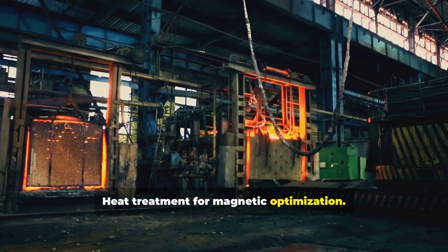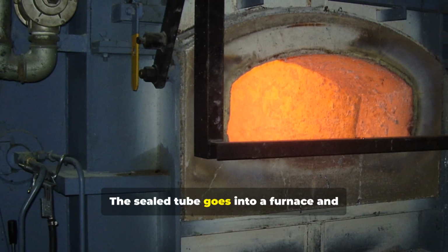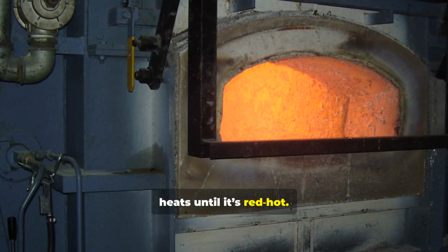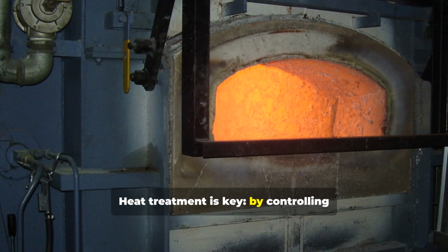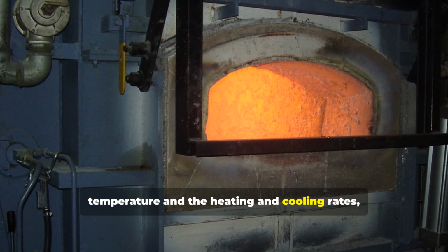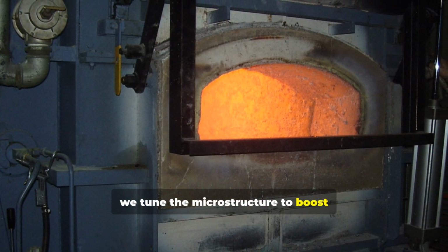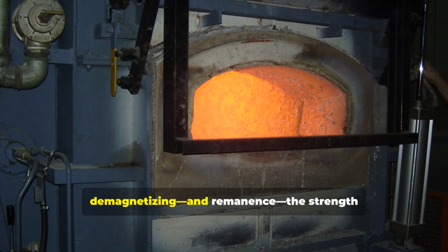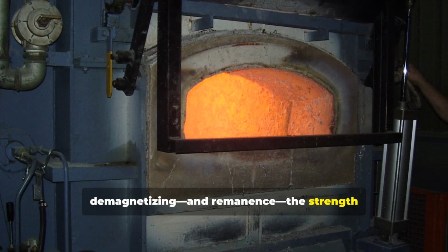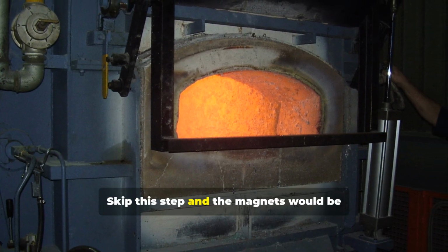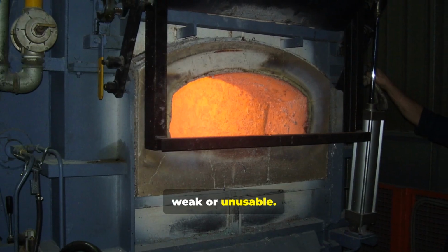Heat treatment for magnetic optimization. The sealed tube goes into a furnace and heats until it's red hot. Heat treatment is key. By controlling temperature and the heating and cooling rates, we tune the microstructure to boost coercivity, resistance to demagnetizing, and remanence, the strength that remains. Skip this step and the magnets would be weak or unusable.